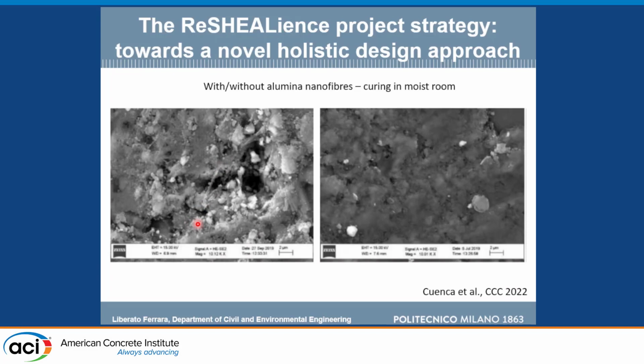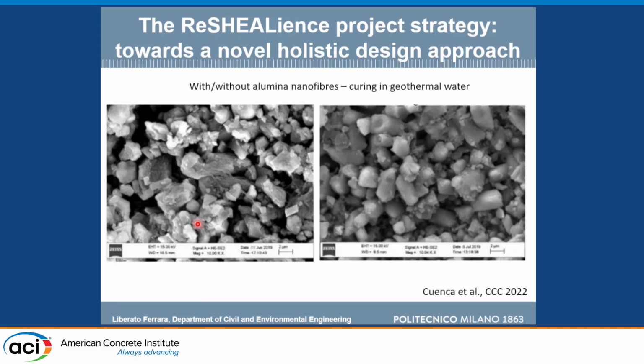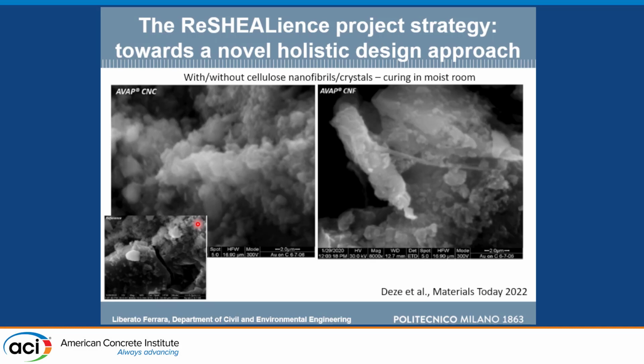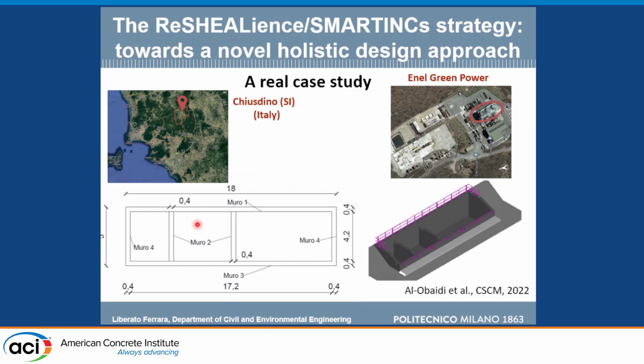The nanofibers also help, but they are hydrophilic, they capture hydration, they foster the hydration of the cement, and this is in geothermal water. And some images also on how the cellulose nanocrystals, the cellulose nanofibrils, really acted as nucleation site for the hydration of cement. So then we went up to scale and design a real structure.